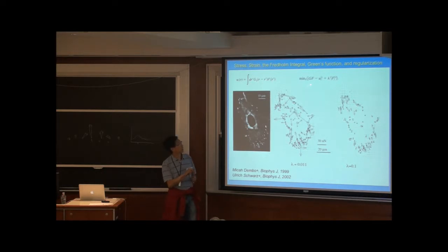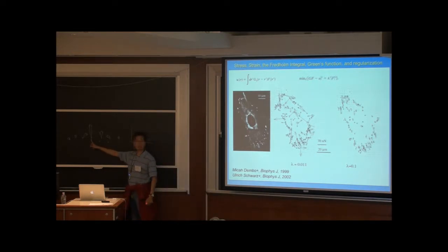So what I can do is I can relax that constraint. I can say, well, I'm okay with having small errors. If I have a point force here and none of the other ones, and I recover my strain field, my strain field is going to be close to the strain field that I had measured earlier, but there's going to be some error.